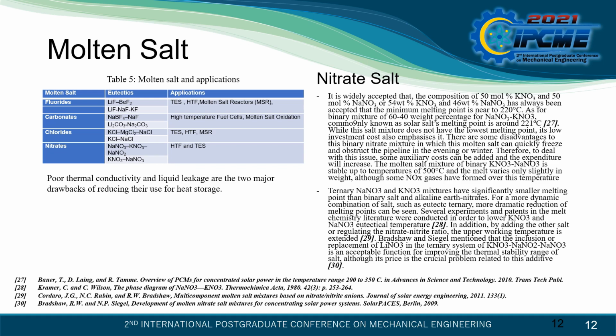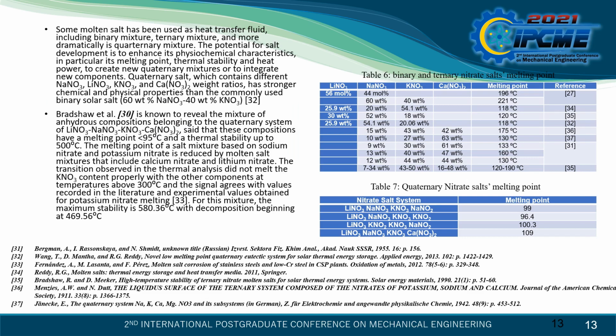In order to overcome these disadvantages, sometimes we add nanoparticles, or we use binary or ternary molten salt, which is more stable compared to a single salt. A few studies have been made on binary and ternary molten salt. Table 6 shows that ternary molten salt has a lower melting point compared to binary molten salt. Table 7 shows that quaternary nitrate salt has a much lower melting point compared to binary or ternary molten salt. This has been discussed by a few researchers.